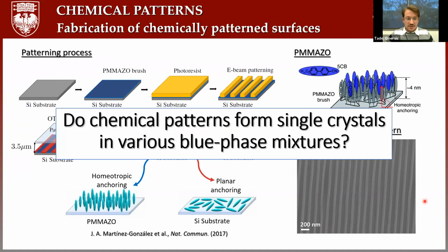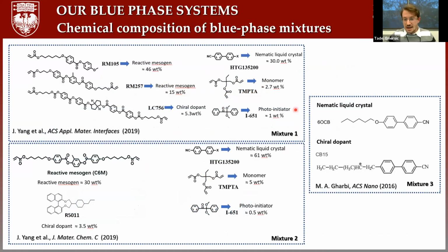And yeah, so people showed this for one particular mixture, but after that we wanted to go a step further, and we asked ourselves if these chemical patterns form single crystals in different blue phase mixtures, right? So to check this, we chose 3 different independent blue phase mixtures, as we can see here. So mixture 1, as we can see here, we have the nematic liquid crystals and chiral dopant. So basically these 2 are enough for the formation of blue phase. But we also have mesogens, monomer, and photoinitiator. This is for the purpose of polymerization that I will talk about later.